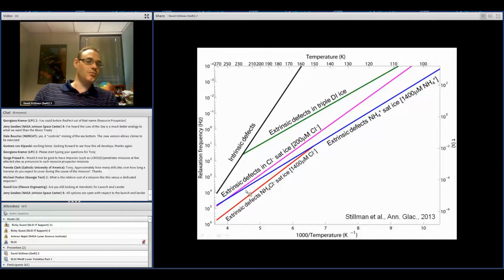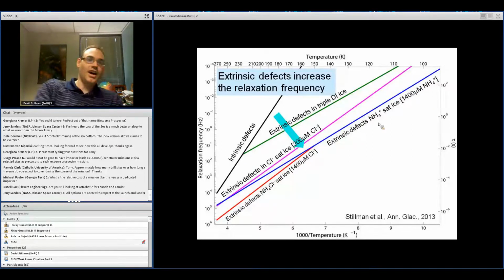Now, if we saturate this ice with 200 micromolar of chloride actually in the ice lattice, then it follows this magenta or purple line here. If we have anything in between saturation and this deionized ice, it will follow this intrinsic line and then bend over, paralleling this green line, and then merge into this magenta line. The only thing that can really get us above that magenta line is if we have ammonium. That allows these charges to move even faster and lets you dump even more of these charges, with a higher solubility. But we don't really expect ammonium on the moon. Anytime you have more extrinsic defects, you increase your relaxation frequency.